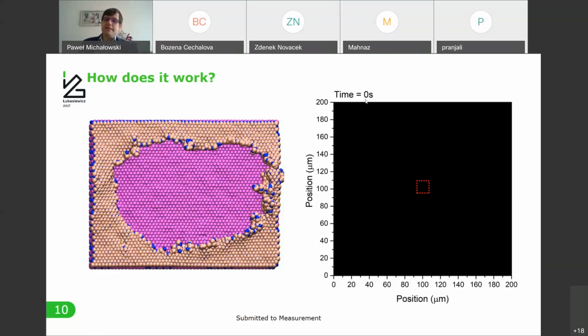This is the signal which will show that all the layers were completely removed and the substrate is exposed. This is shown here. But first, for a very small region, I pre-bombarded it with a high energy ion beam, but with an extremely low intensity. So I introduced a lot of defects in this area, but I did not sputter it yet.